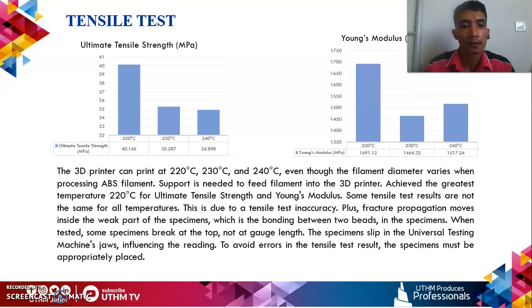This is due to tensile test inaccuracy. Plus, fracture propagation moves inside the weak part of the specimens, which is the bonding between two beads in the specimens. When tested, some specimens break at the top, not at the gauge length. The specimens may have slipped in the universal testing machine's jaw, and it will influence the reading. To avoid errors in the tensile test results, the specimens must be appropriately placed.